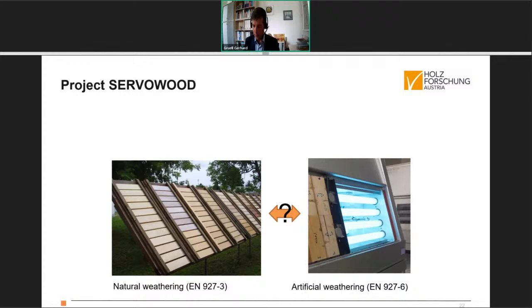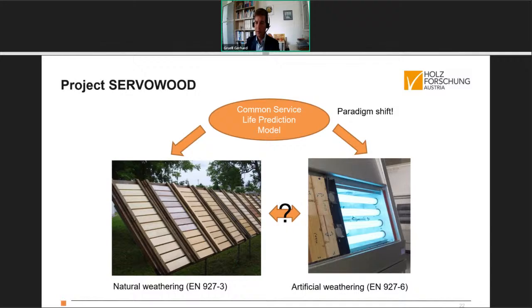A more serious approach on service life prediction was made in the large European project SERVOWOOD, involving 5 institutes, 5 associations, and some SMEs, involving 52 coating systems with known formulation, 5 wood species, and so on and so on. And the approach of this project was, again, to find some connection between artificial weathering and natural weathering, and also laboratory testing. But we wanted not just to correlate, we wanted to find a common service life prediction model, a common dosage model for these different kinds of exposure tests to be used universally for both approaches.